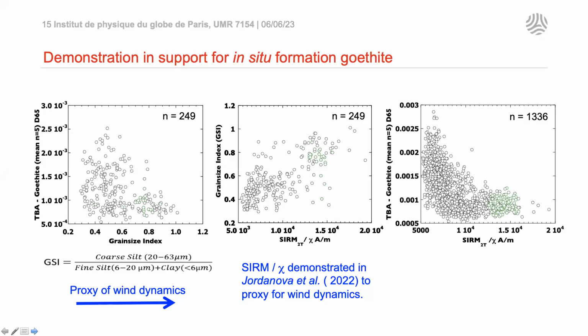In the middle plot, we're testing what I said already was our magnetic wind dynamic proxy against this sedimentological wind dynamic proxy. And it's not a fabulous correlation, but you can see a tendency of a linear increase. There's a linear correlation, but it's weak because we're seeing two populations. But again, there's only 249 samples because we only have 249 grain size determinations so far of the 1,336 samples that we have for the full section.